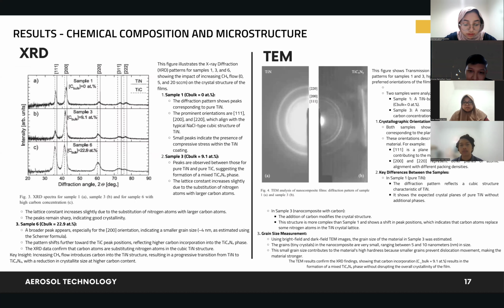Now the results are analyzed using XRD and TEM. Here we can see the diffraction angle and also the intensity. Samples 1, 3, and 6 indicate that the increasing CH4 flow introduces carbon into the TiN structure, resulting in a progressive transition from TiN to titanium carbonitride, with a reduction of crystalline size at higher carbon content.